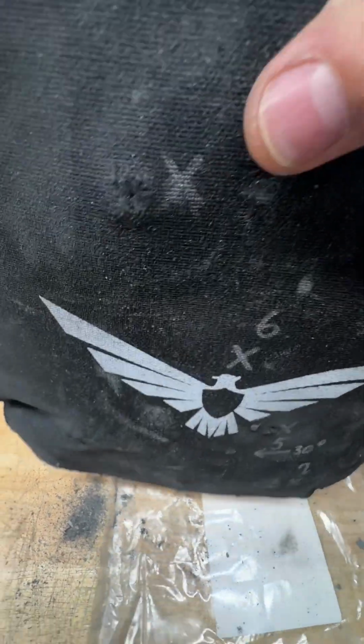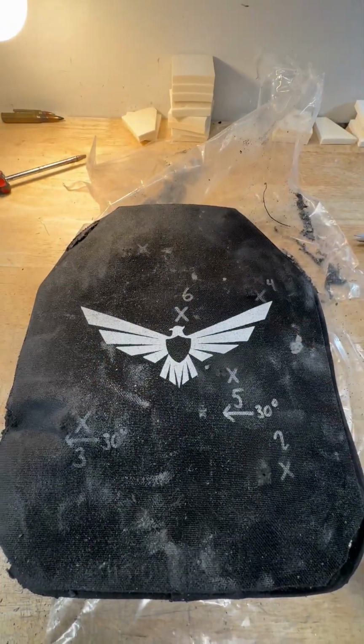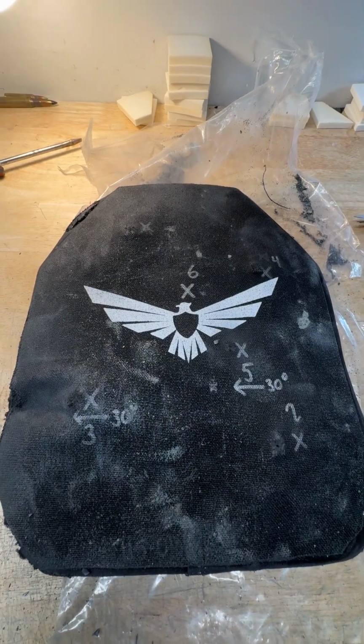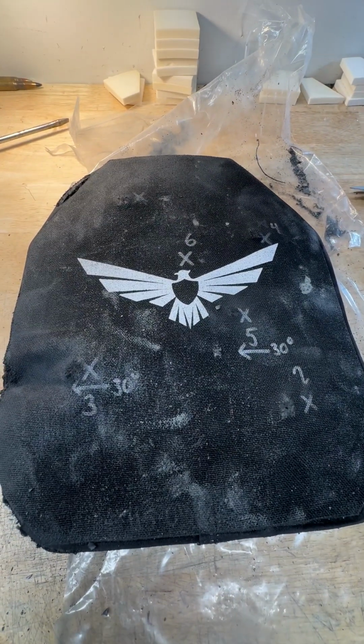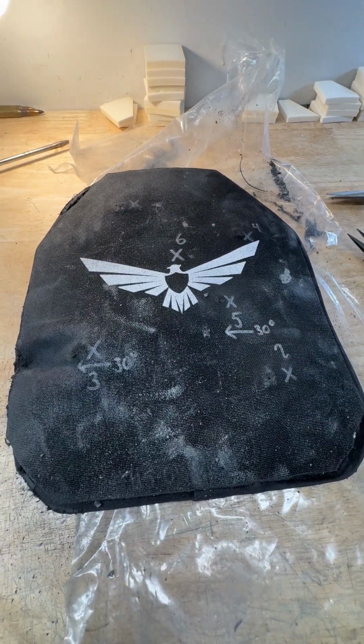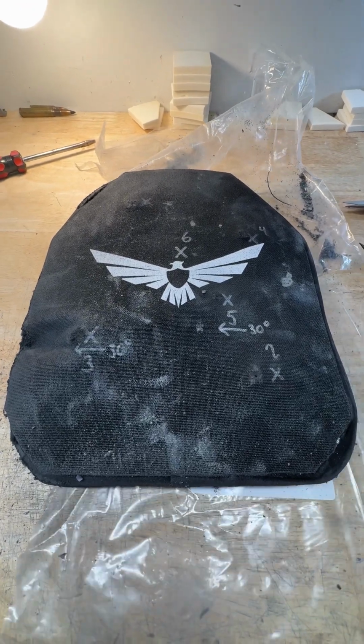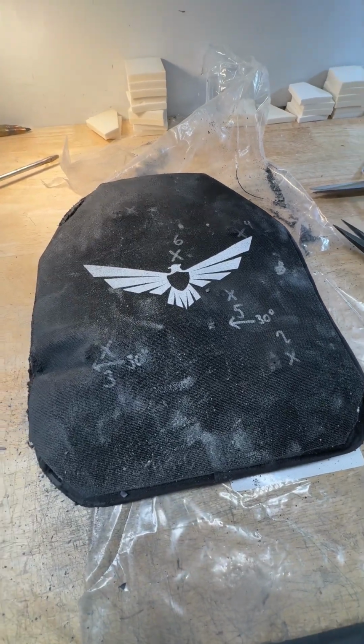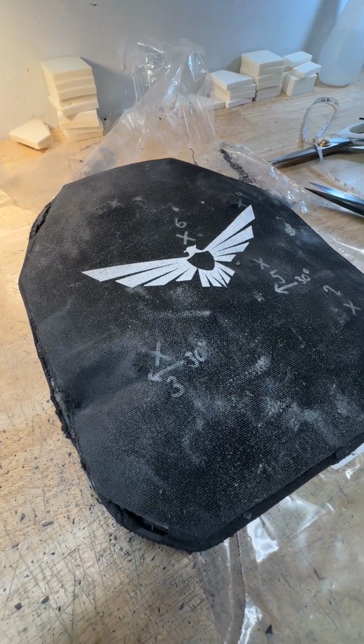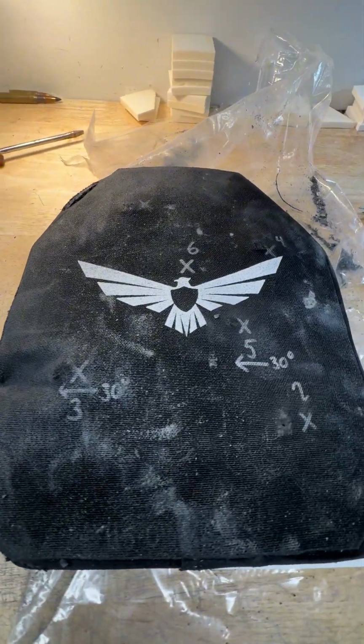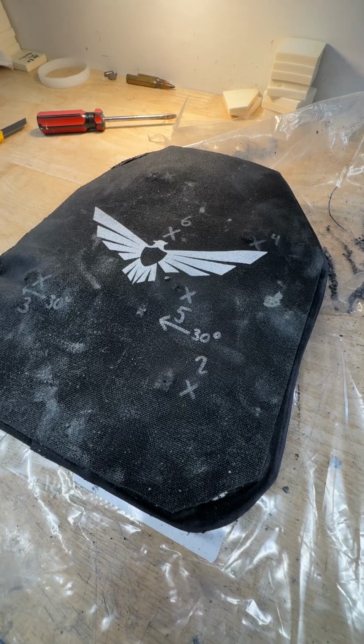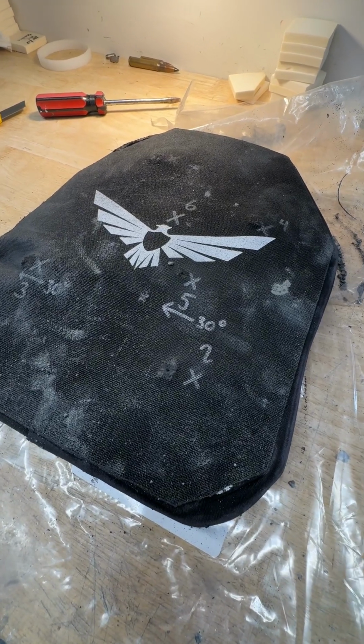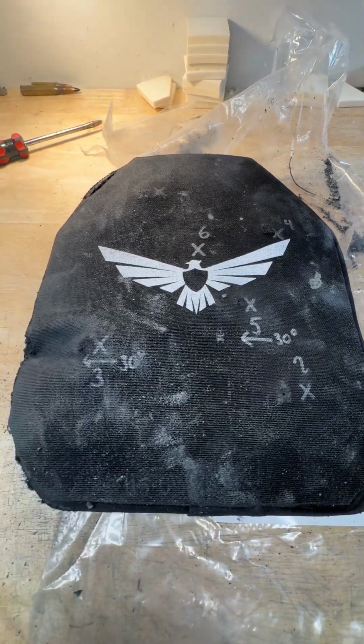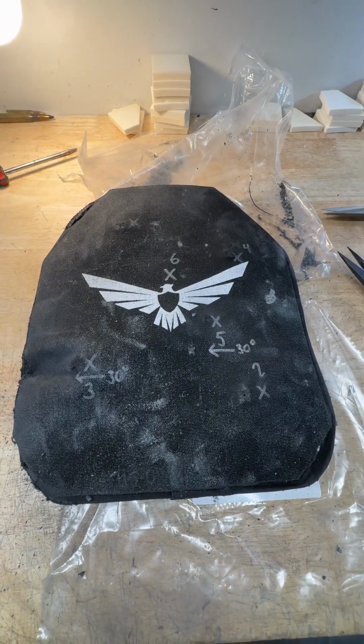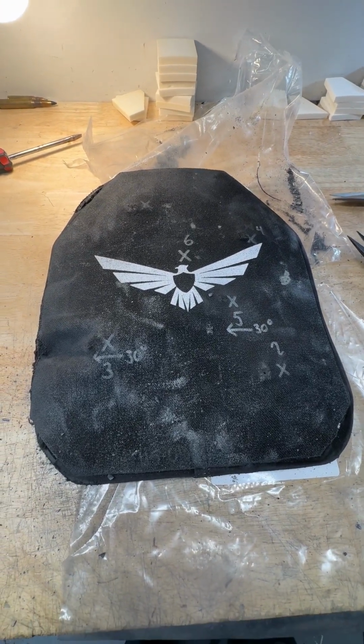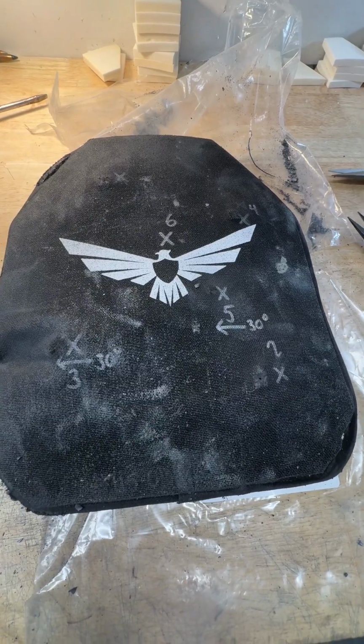Very nice result, and it looks like our crack arresting layer with the monolithic plate combined with the adhesives and the trauma reducing layer is enough to improve the performance of a monolithic. But be aware that most manufacturers do not do these things. They do not apply crack arresting technology, and they do not apply trauma reduction layers, so you will not get the same performance from other monolithic plates. But let's take this thing apart and have a look.